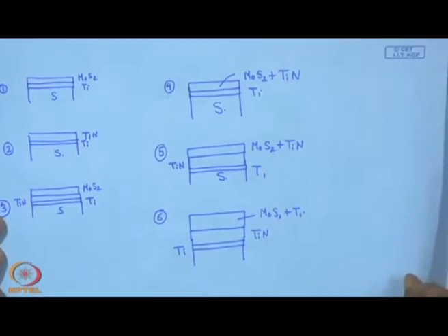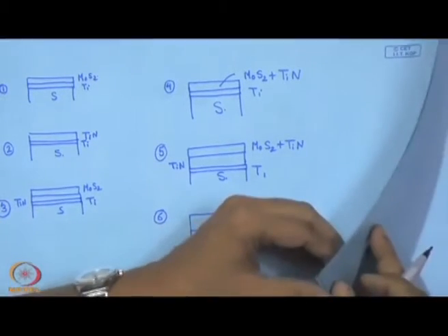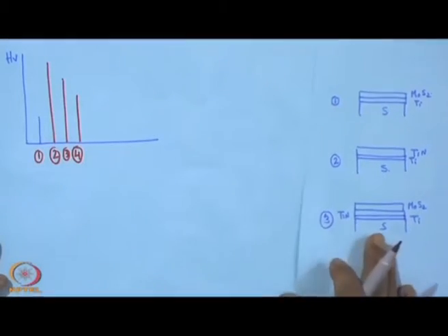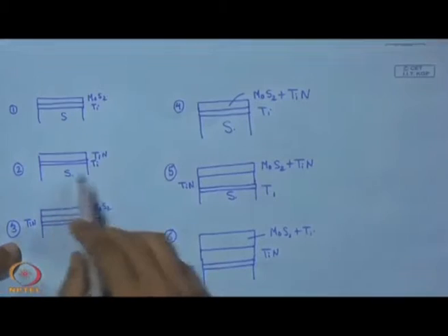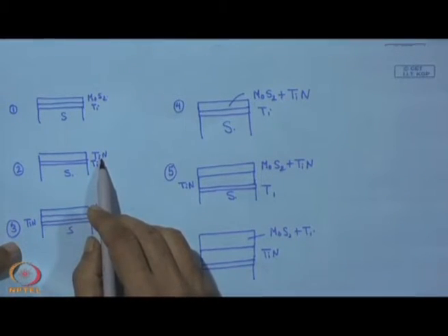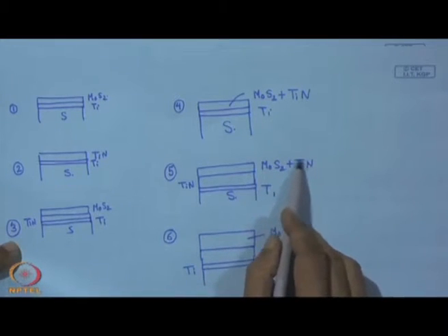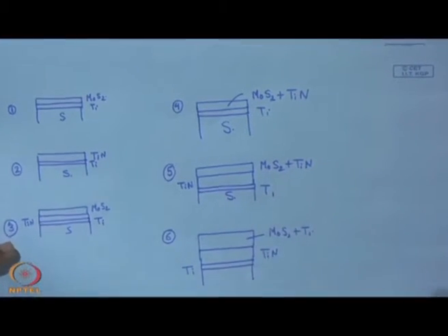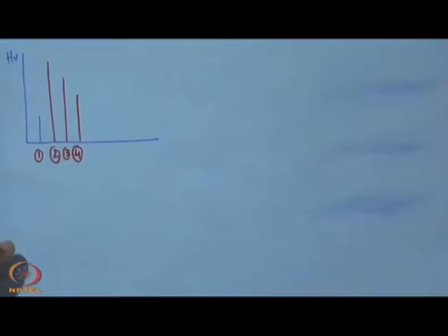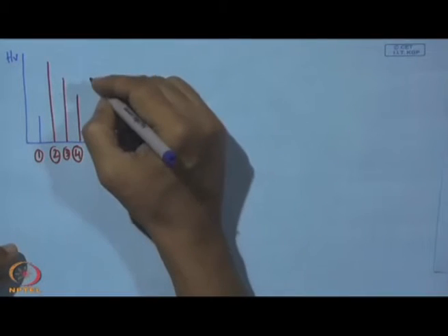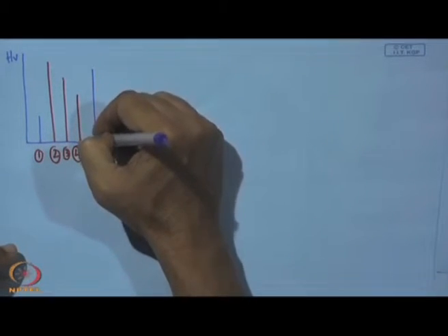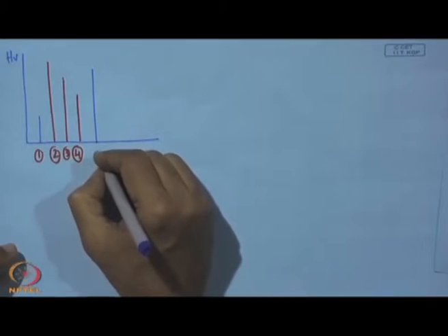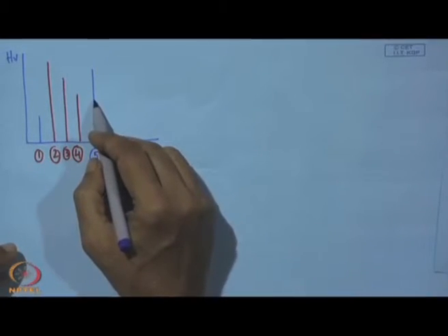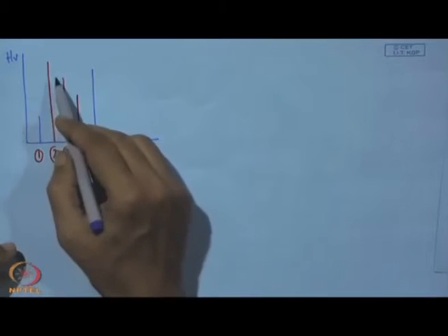So, with this we expect a hardness which will definitely exceed that of 3 and 4, but it can be less than 2 because it is top TiN and it is just a composite. So, it has its own effect, and as a result we have this hardness which will be somewhere here. So, this is 5. So, architecture 5 will give a hardness more than 3 and 4, but less than 2.